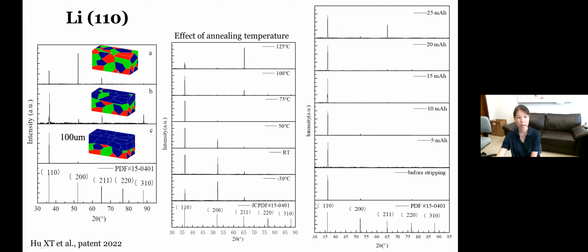So A is the one with the pristine lithium foil, which has a random texturing, and B shows the preparation results after the pre-rolling and the scraping. So that is to create a certain amount of shear texture. You see the dominance of the 110 diffractions in the X-ray pattern, right? And the last stage is to initiate the recrystallization process of the material, and that will give you the dominance of the 110 texturing, right?